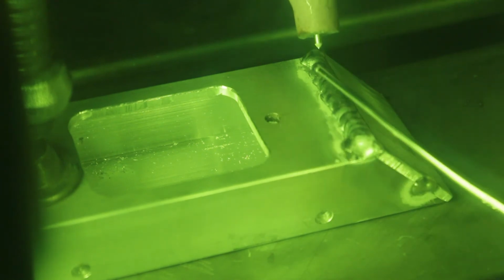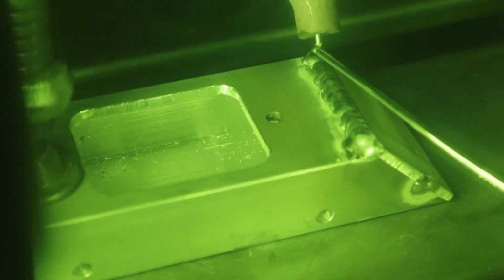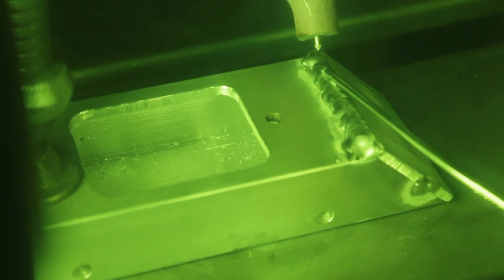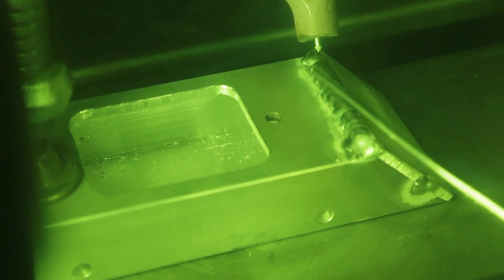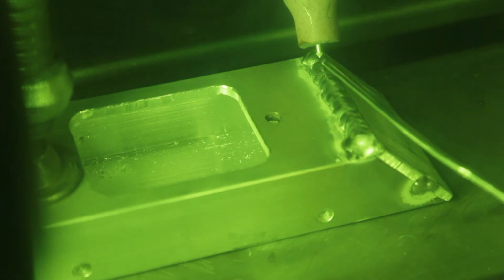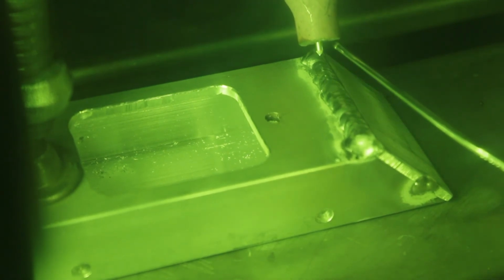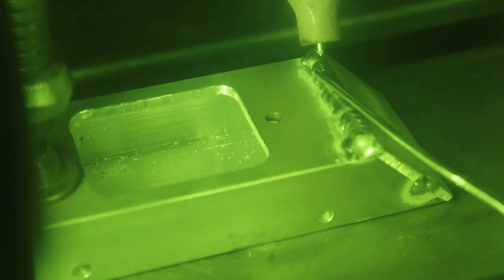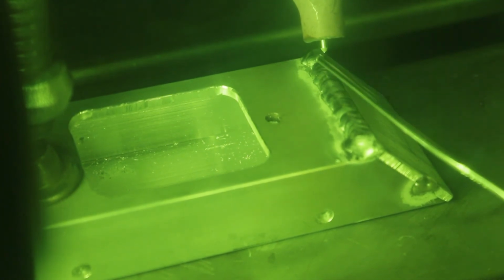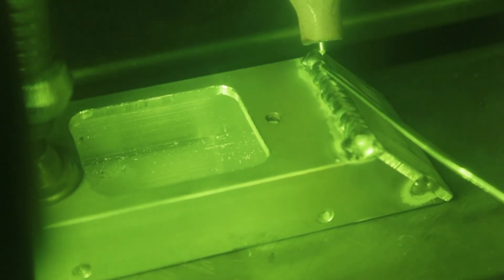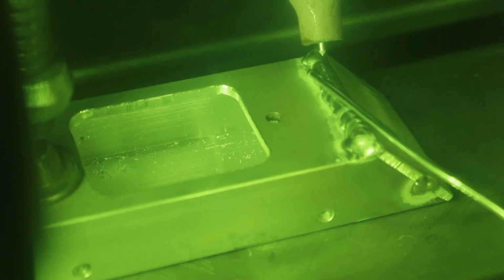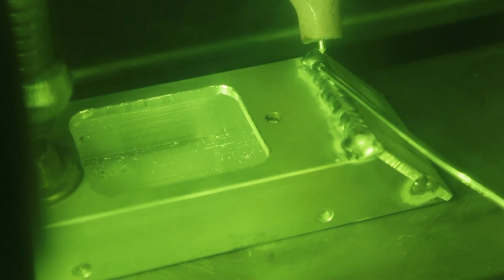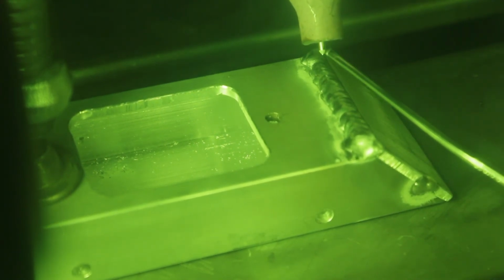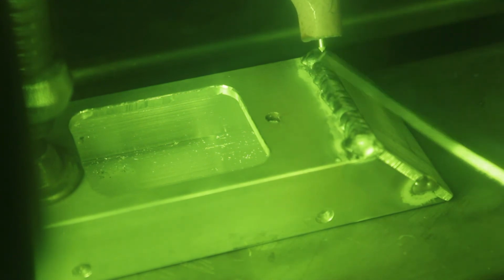So while you're welding, you want to make sure that the tungsten, this tip of the tungsten, does not touch your base material or your rod. So as you're welding, you want to make sure that you don't touch it like this or you touch it like this, because then the aluminum will get on top of the rod and you won't make a good arc between the tungsten and the aluminum. If it does happen, then you can take this tungsten out and take it to the grinder and grind the tip down again sharp.